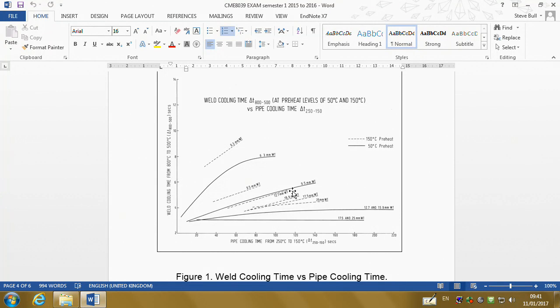What it means practically is people actually measure this. They have a temperature probe on the pipe, and they will heat a piece of pipe up to a certain temperature, and they will measure the temperatures by depositing weld metal on the surface and the pipe cooling, just to check in the environmental conditions that you're doing the weld that you get the behaviour that you're expecting. And it has to be checked actually in the environment that you're doing the weld. So if you're welding onto a live pipe, you bring a pipe pup in and you do a weld next to the pipe, and you check that, and then you might even weld onto the surface of the live pipe a small amount of material, and you check that, and you make sure everything works with what you're expecting before you go and do the real weld that is going to be significant for your asset.